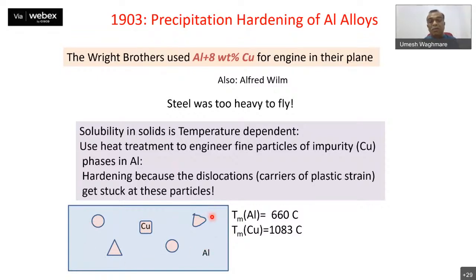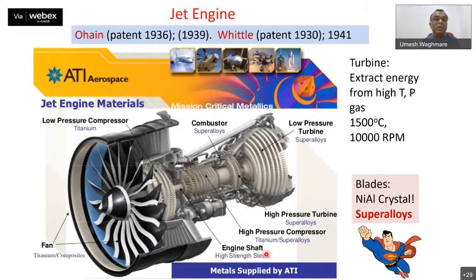Dislocations and defects, which mediate mechanical behavior or plastic strain, are basically stuck at these interfaces, giving it lightness as well as strength. So this is key. Again, without this material, one couldn't fly so easily. The invention, which was so superb, wouldn't have been possible but for these materials.